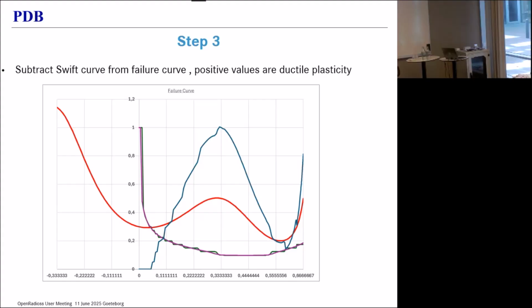So the blue curve is a normalized measure for the ductile plastic deformation, the amount of plastic deformation that will give rise to mesh dependency. And we've normalized it here for a triaxiality of 1/3. We've normalized it to a value of 1.